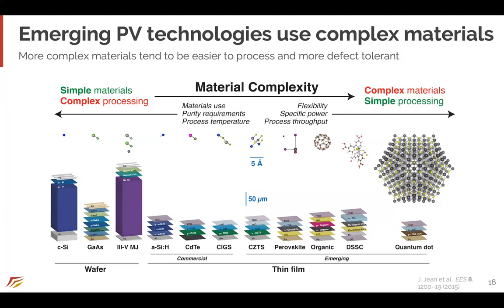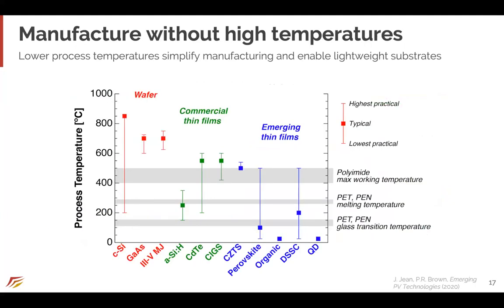And these materials on the right side, these emerging materials, including perovskites, tend to be more abundant. They tend to be more tolerant to impure precursors and disorder, so you can manufacture them more cheaply in many cases. And those lower manufacturing temperatures are a big advantage. Perovskites and other emerging technologies can be manufactured at below 200 degrees Celsius, compared to 500 plus for silicon and commercial thin films like CdTe and CIGS.